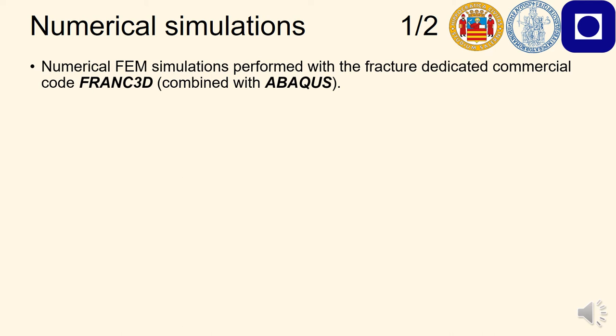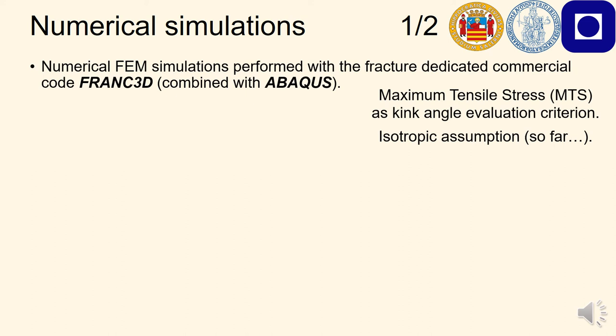Now, we are going to see the numerical simulations we performed with the commercial code FRANC3D. FRANC3D was used as a fracture dedicated code, while Abaqus was used as the finite element solver. The kink angles were calculated through the maximum tensile stress criterion, and isotropic assumptions were made so far. These are only preliminary assumptions, and further improvements are already under development.